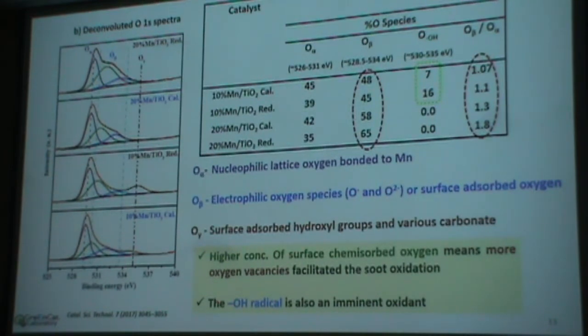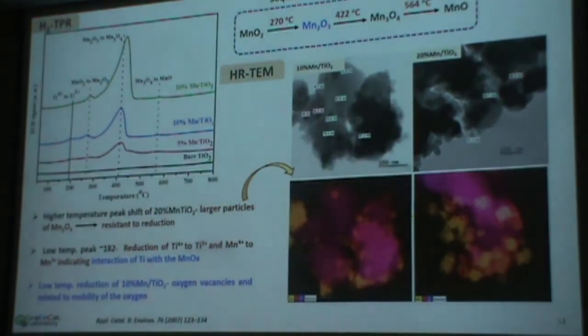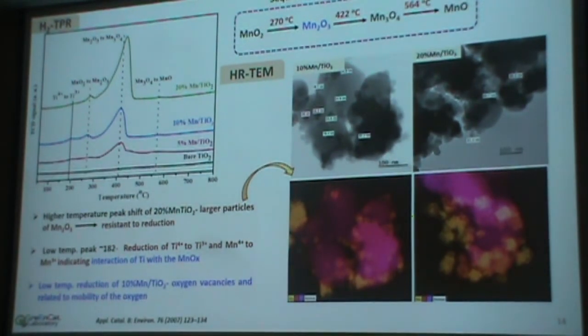Actually, lattice oxygen is also participating in the oxidation reaction. In some reports it was stated that Mn enhances the mobility of lattice oxygen, and that leads to the generation of new active oxygen species. So we cannot state from this data that only the surface adsorbed oxygen species are active. That means an optimal combination of Mn species and surface adsorbed oxygen species is important for the soot oxidation reaction.